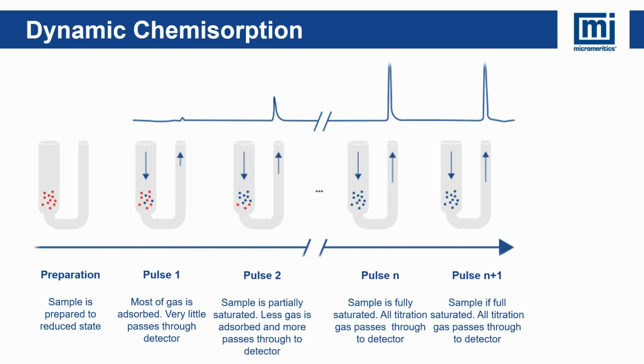The dynamic chemisorption process is relatively straightforward. Similar to static chemisorption, the first step involves cleaning the surface of the platinum-alumina catalyst, followed by a reduction reaction at 400 Celsius. Once the catalyst has been reduced, a purging step is employed to remove any remaining hydrogen gas. The sample is then cooled to the analysis temperature of 35 Celsius. The analysis begins by pulsing a known amount of probe gas into the system until the reaction reaches the saturation state.